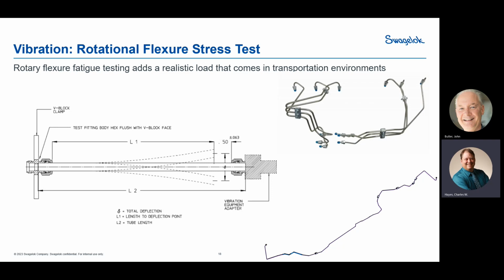Now, how do I go ahead and do this? Well, this test is actually pretty cool because what you do is you put a strain gauge on the tube right here, and you measure the strain in the tubing because every tube might have slightly different strain, and you set your offset based on that. So your distance that you're going to make this rotation happen. The test is both an SAE AS standard and an ASME standard for the test protocol. It'll tell you what those stress concentrations you want them to be, and then you go ahead and run the test. The other cool thing is that you can pressurize this and actually pressure cycle it while doing the test. That's a real test to see how things are going to fail.